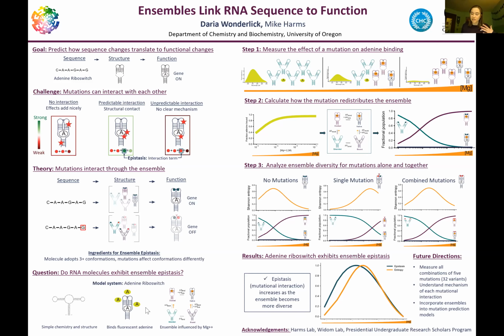And further, I can change the size of the ensemble by adding magnesium to selectively stabilize only 2 of the states. So if the ensemble is generating mutational interaction in this system, I expect that reducing the size of the ensemble will reduce these interactions. So to look for ensemble epistasis, I first have to detect the effects of mutations on adenine binding. And so I do this by measuring how fluorescence changes as a function of magnesium concentration. So at high levels of magnesium, there is a larger ratio of the conformation that's capable of binding adenine. And so this means the fluorescence is going to decrease, and different mutations alter this rate of fluorescence quenching.